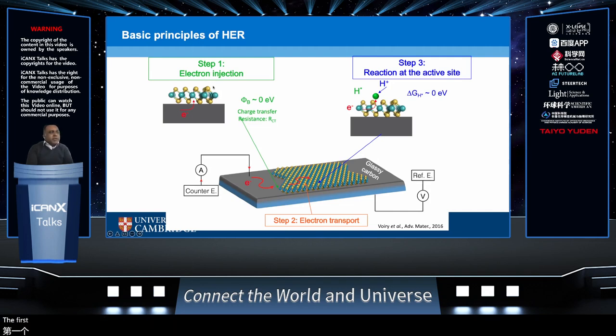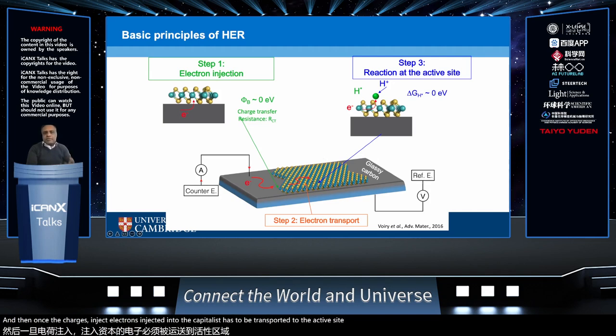So the first step in a HER reaction is that electrons are injected into the catalyst from our substrate. When the substrate is held at a cathode potential, the electrons are injected. What this means is the electrons from the glassy carbon have to go into the catalyst, in this case the metallic phase MoS2. And so that electron injection step is essentially the charge transfer resistance, right? Transferring charge from the substrate to the catalyst. And then once the electron is injected into the catalyst, it has to be transported to the active site. The entire surface is not catalytically active.